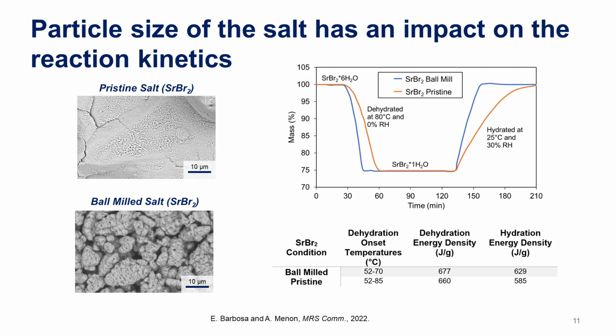The other factors that impact this is the salt structure itself. You can see the particle sizes can tend to be fairly large. If we ball mill the salt, this is strontium bromide, we can create much larger surface area. You can also see much more porosity in the structure once it's ball milled. Down to about 10 micron size particles,